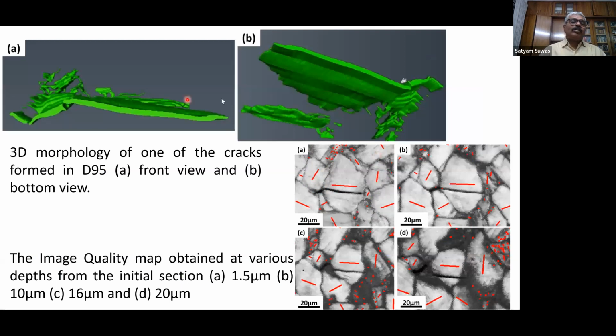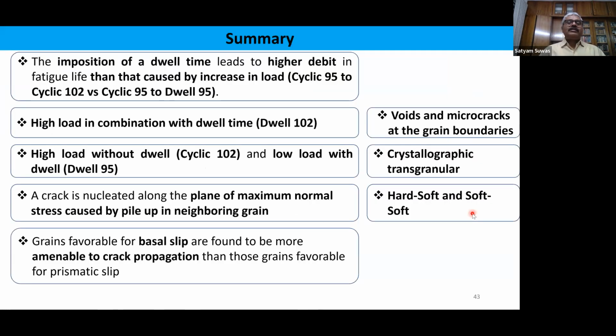And we also extracted the morphology of cracks, right? This is what is shown here. We analyzed so many cracks, and a lot of data were generated in this case. So this exercise has led to the conclusion that the imposition of a dwell time leads to a higher debit in fatigue life than that caused by an increase in the load, that is cyclic 95 versus cyclic 100 and 102, meaning over and above yield stress, versus cyclic 95 versus dwell 95. So dwell time is the main culprit in this case.